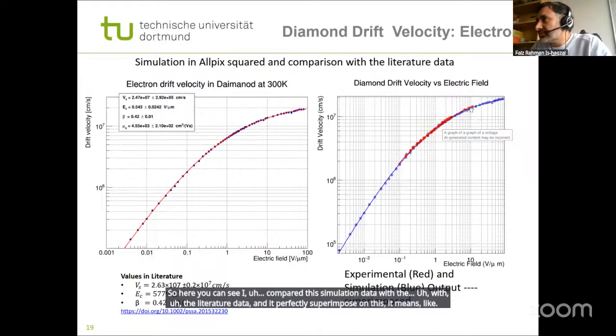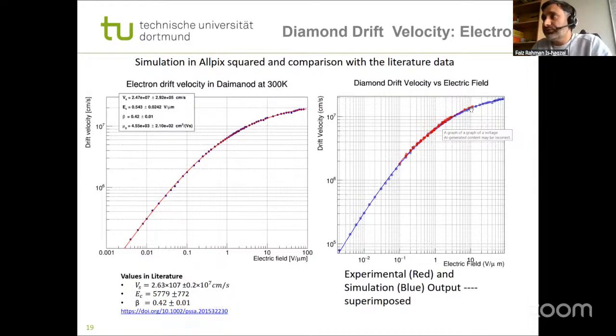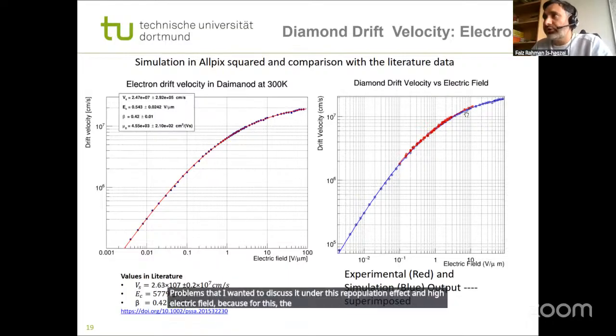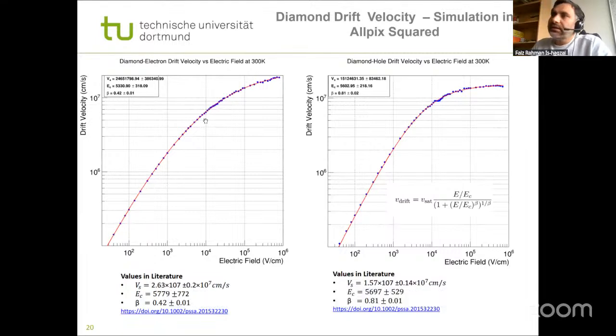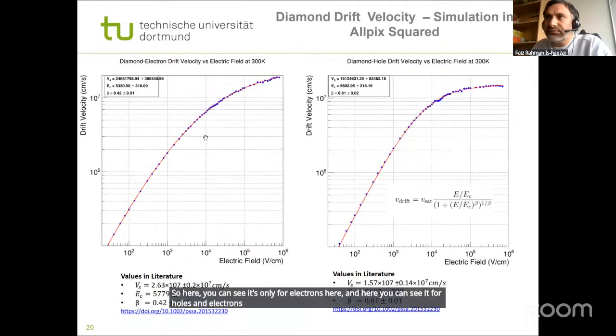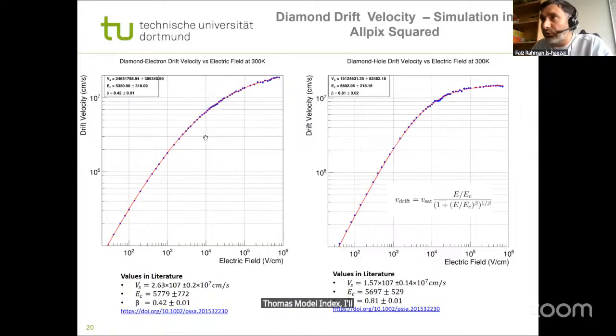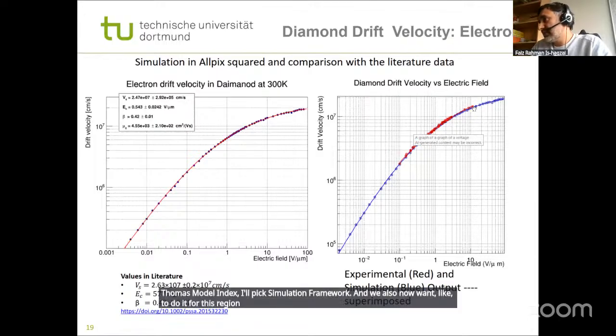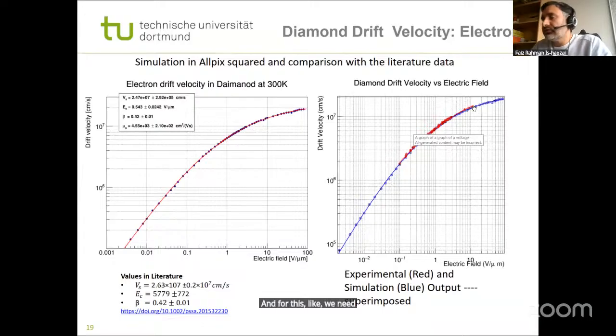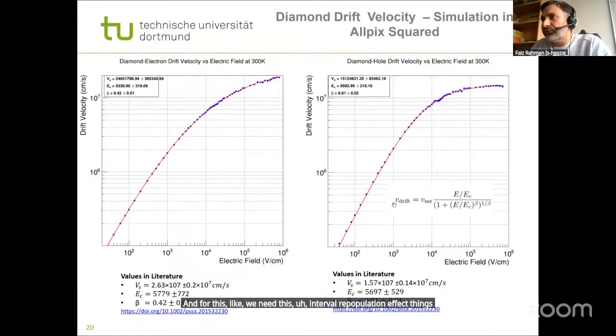It means it works, but here we can see a little deviation at high electric field, and it's because of some problems that I wanted to discuss, namely the intervalley repopulation effect at high electric field, because for this the Caughey-Thomas model doesn't work. Here it's only for electrons, and here you can see it for holes and electrons, so we successfully implemented the diamond material and the Caughey-Thomas model in the Allpix Squared simulation framework. We now also want to describe this region, and for this we need to take the intervalley repopulation effect into account.